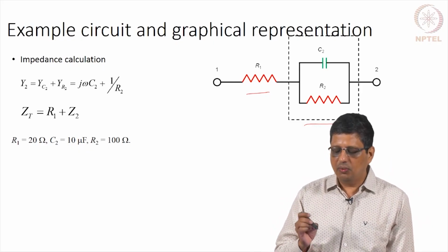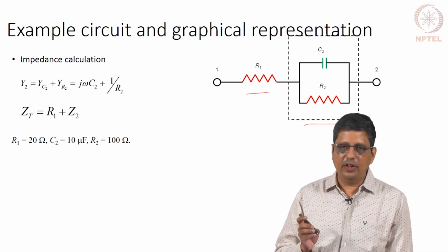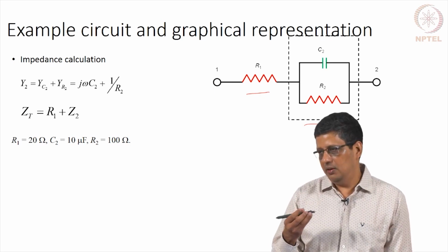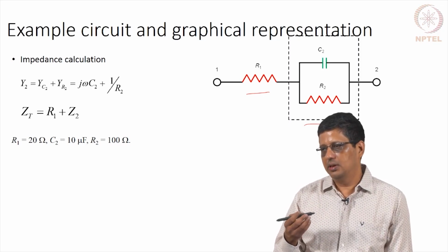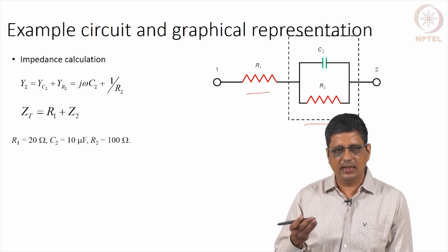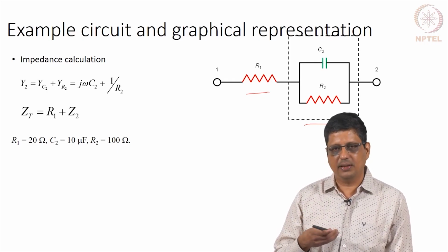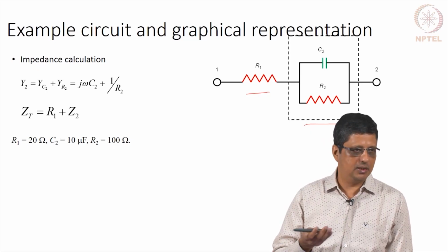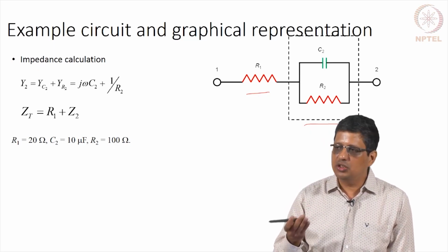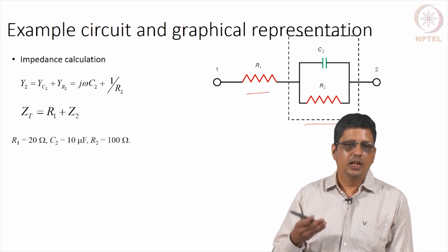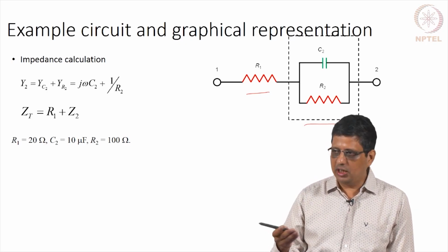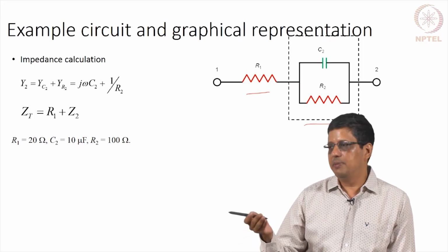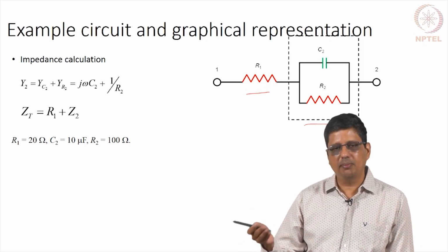Let us think, what do we expect to see when the frequency is very, very high or very, very low. Typically, we use 100 kilohertz, 300 kilohertz, 1 megahertz at the high frequency in an electrochemical impedance spectrum. Low frequency depends on how long we are willing to wait and how good the system is. We will at least go till 100 millihertz, 0.1 hertz. If the system is good and we can wait for a long time, we will go to 10 millihertz, 1 millihertz, 100 microhertz. The best instruments say they can take data up to 10 microhertz.